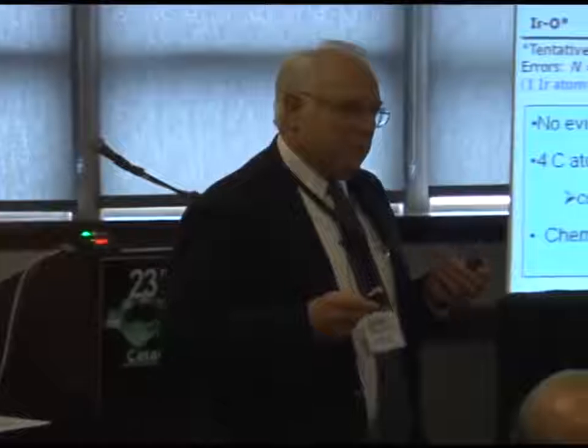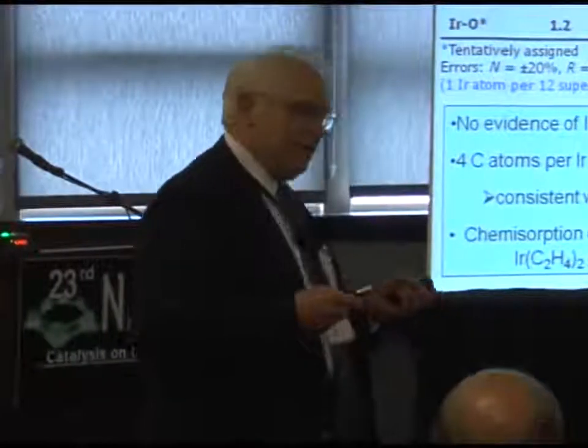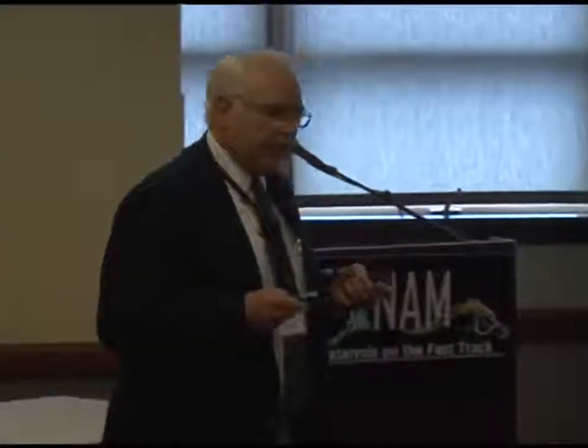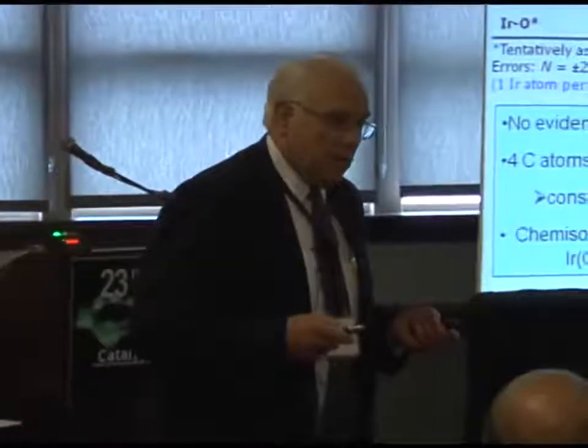The iridium-oxygen coordination number is about 2, and it means that we've replaced the acac, which you can see with infrared spectra on the surface. It's replaced the acac with the support: 2 oxygen atoms of the support bonded to the iridium.